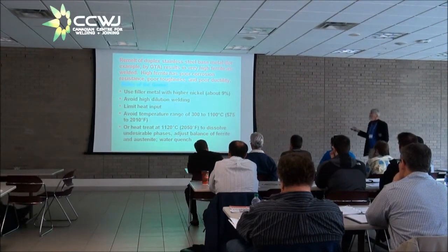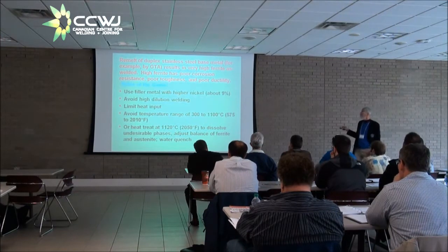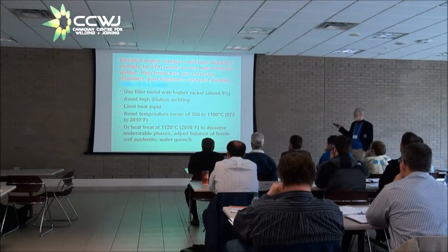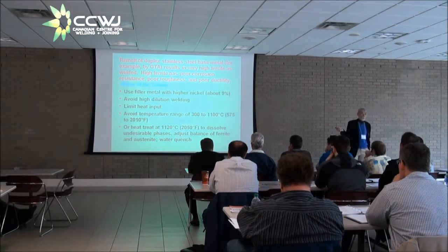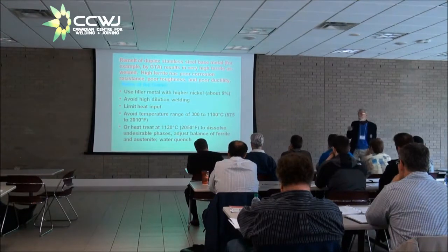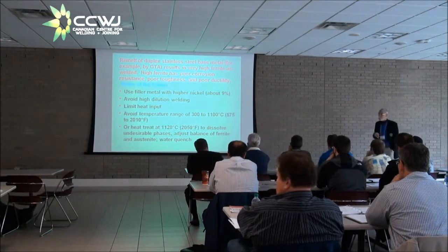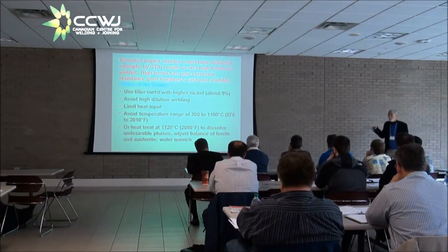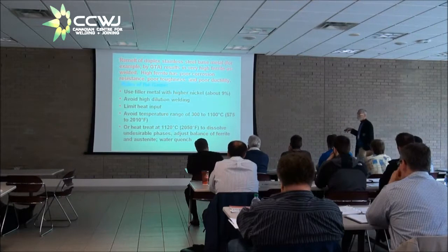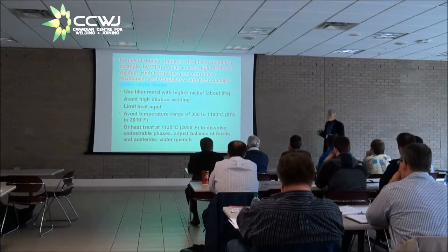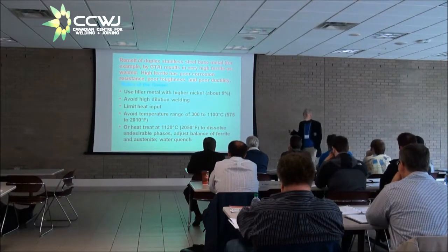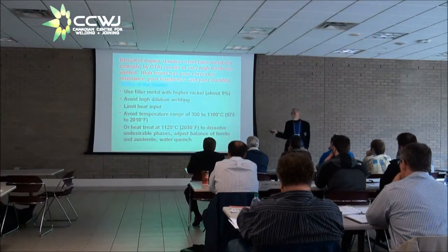So the rules of the game to weld duplex stainless: high nickel filler material, avoid high dilution welding, or if you are going to do high dilution welding, you're going to want to anneal afterwards. You know, the longitudinal seam in pipe is oftentimes welded by a plasma arc keyhole with no filler metal or very little filler metal, or by submerged arc with very high dilution process. And as long as you anneal the pipe afterwards, that's just fine.